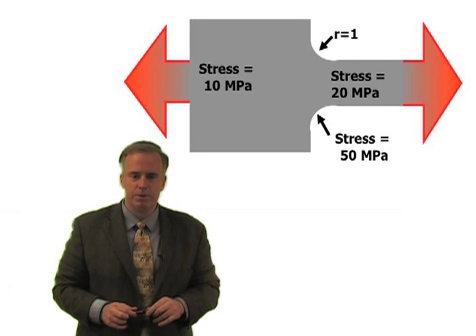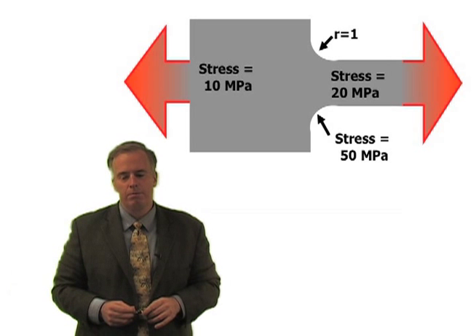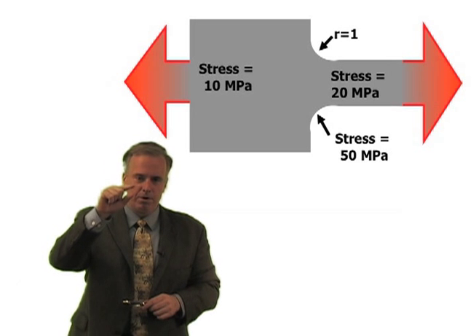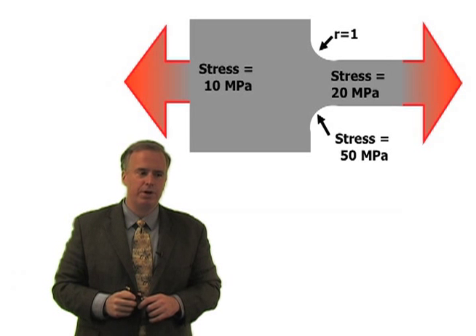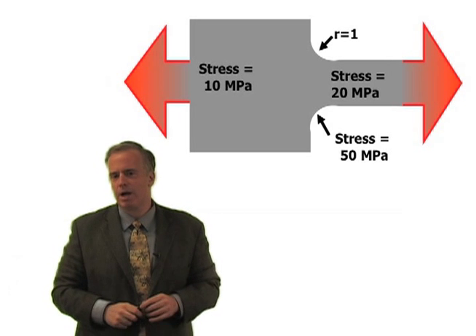So if we look here and we take a part, there are lots of different stress concentrations. But if we take that same part and we pull on it with a certain stress, if that part has a very large radius, then that stress concentration or that magnification of the stress, that's not going to be that big.